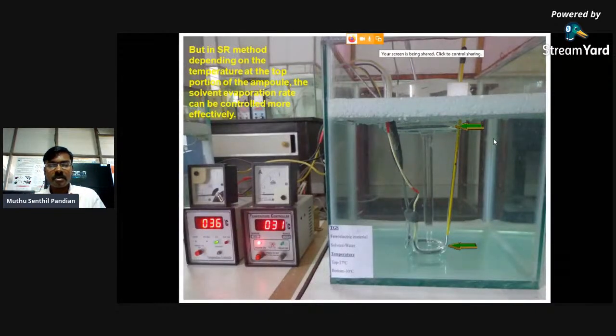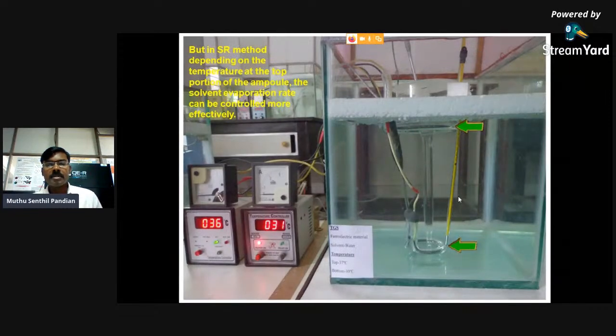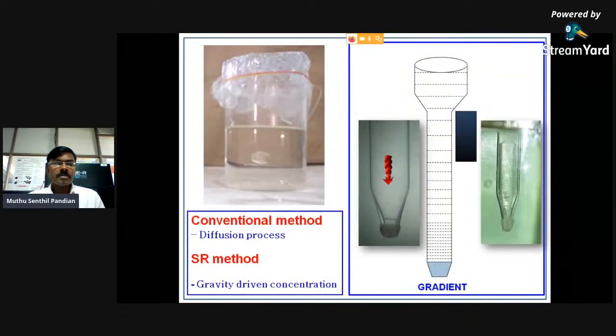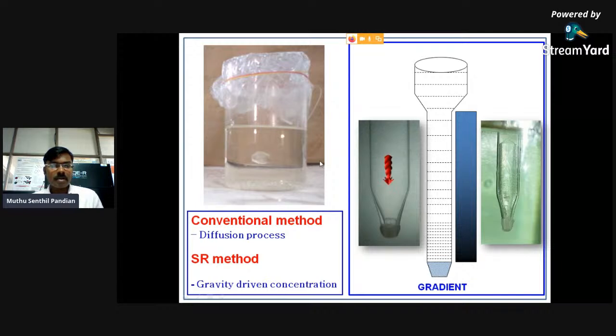But in the case of the SR method, as I told you several times, we have maintained the temperature at the top and bottom portion. So stable temperature, stable supersaturation, stable evaporation rate. There is no solvent inclusion in the case of the SR method, compared to the normal conventional slow evaporation solution growth method. In the conventional method, normally the crystal will be grown like this. This is the submerged seed solution. This is the conventional method grown crystal. In the conventional method, the crystal will be grown normally like this in the diffusion process. So the availability of material ingredient is less in the conventional method. But in the case of the SR method, after 3 hours, due to gravity-driven concentration, all the solute molecules are approaching the crystal surface directly. So this crystal surface attracts more atoms very easily. So there is no solvent inclusion in the SR method grown crystal.